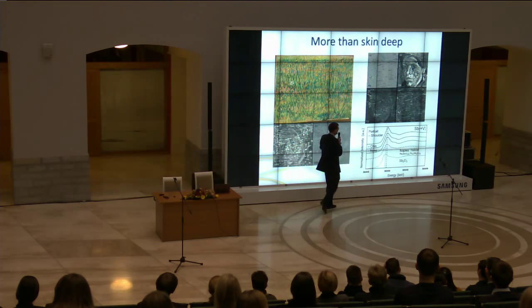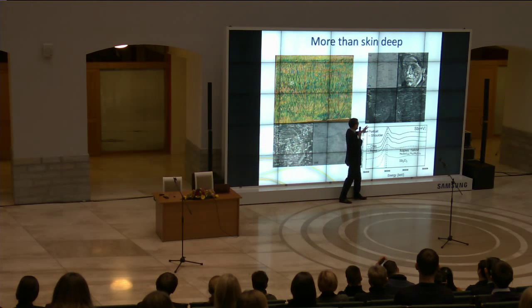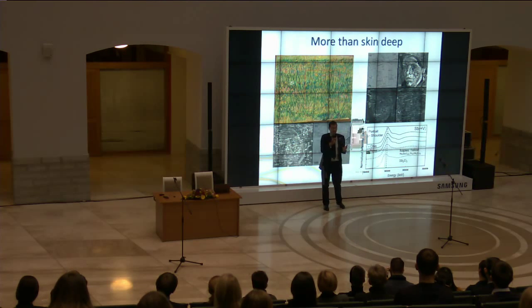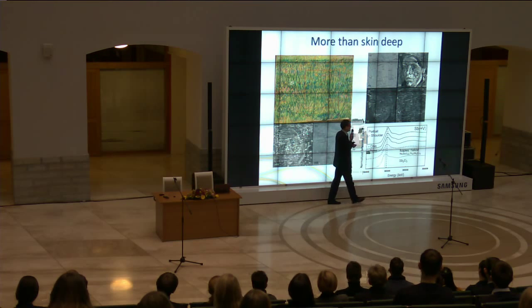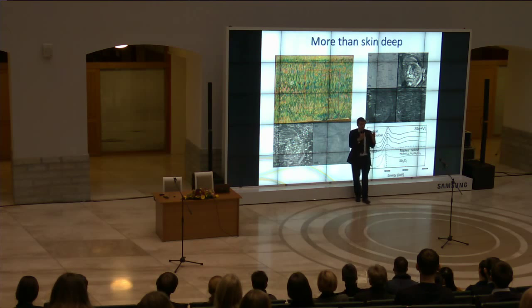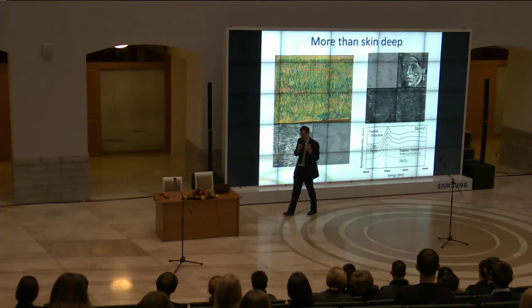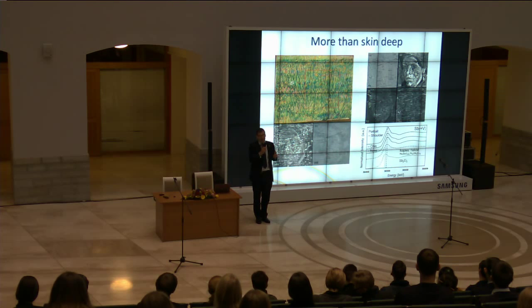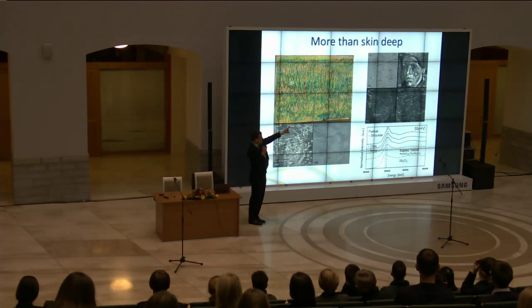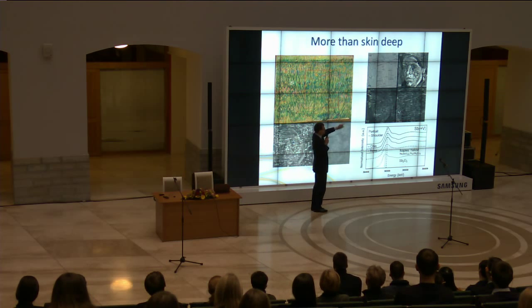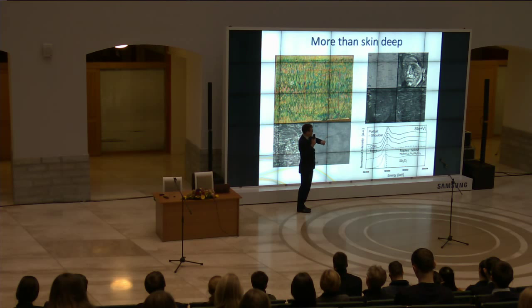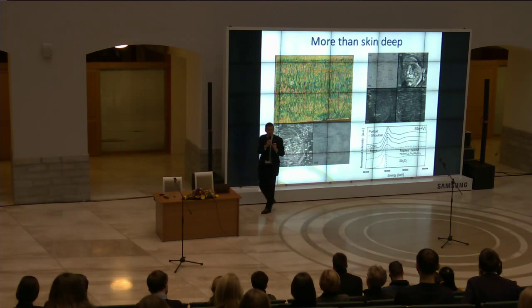And if you carry on that process, you can show, now I'm blind, so I don't see this very clearly, but you can see that the mercury is found on the lips, not surprising, because mercury is the common base of red pigments, and there is also zinc, which is a white, usually used in a white pigment, around the eyes. So one question is, what form does the antimony take? And you can use very precise synchrotron X-ray measurements to say, not only is the element antimony, the chemical symbol for that is Sb, not only is there antimony distributed like in the top right figure, but you can even look in greater detail at what form of antimony is present.